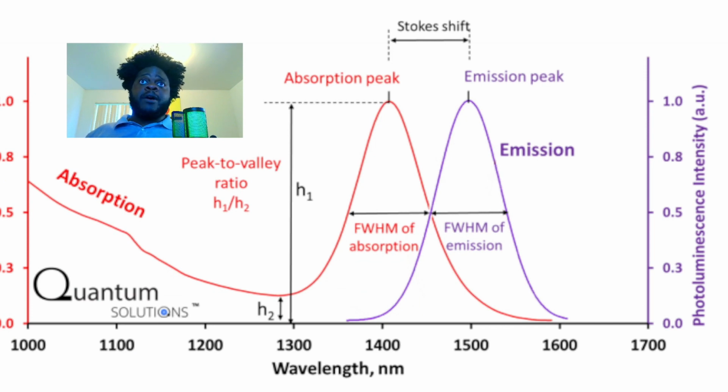Next, there's something called the emission or photoluminescence spectra. That is where they are, the energies that these quantum dots are emitting light at. And so you see it has some width. It's defined in science as the full width half max. It's the width at half of the maximum intensity of the peak. And this also has information in it. This is telling you things like the size dispersion of the quantum dots.